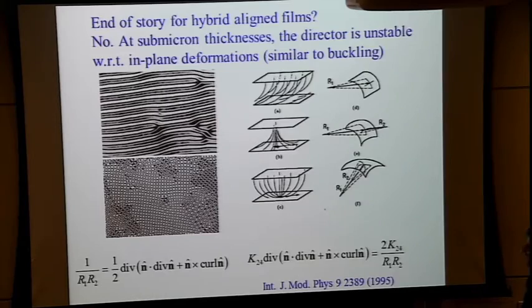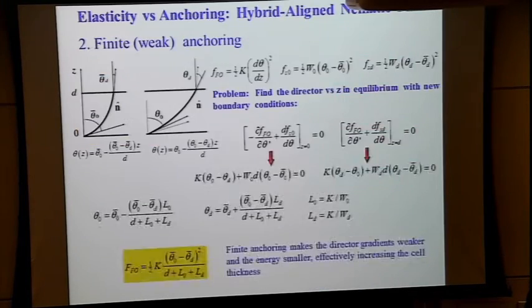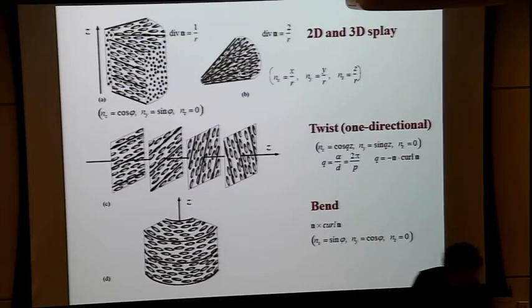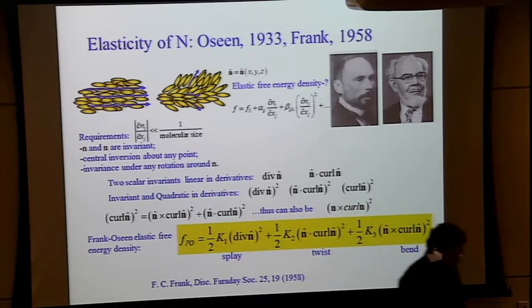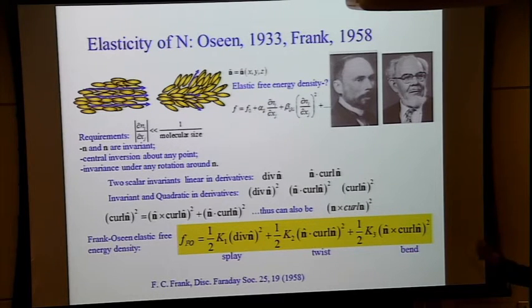So in our experiments, it was like 0.9 of K1, if I'm not mistaken. So there are also some important things to remember. Like you see, I didn't specify because at some level it's obvious. So the values of elastic constants must be positive definite, right? Because if K1 is negative, then the nematic will develop spontaneous deformations trying to make divergence n as huge as possible because it comes with a negative sign in front of it.